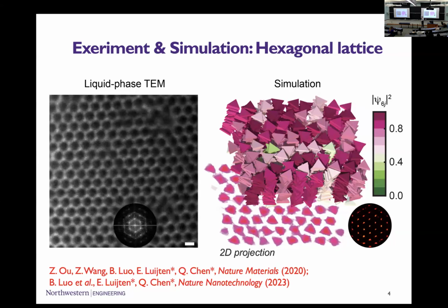And the first thing to note here is these particles are so small that you can actually get pretty close to a decent prediction of the true particle-particle interactions. Because you can essentially imagine this particle built up out of atoms, gold atoms. You know the van der Waals attraction between gold atoms, and you can just sum over all atom pairs between the two particles.